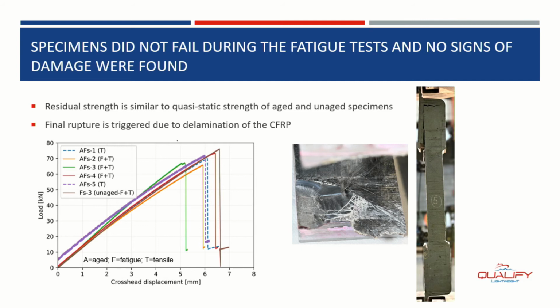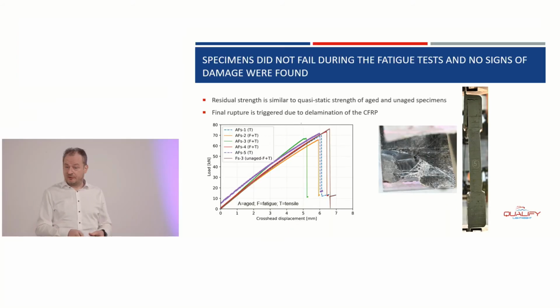But if you look at all these graphs, you see that the evolution of load versus elongation or displacement is always the same, and the final strength is again not different for aged, unaged, fatigue tested or non-fatigue tested specimens. So we have quite reproducible strengths.